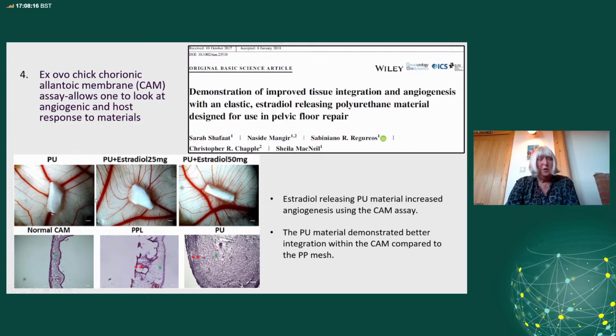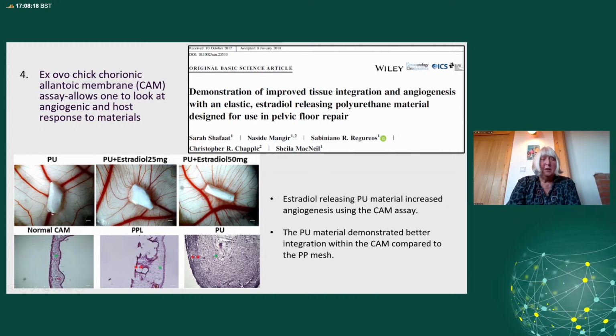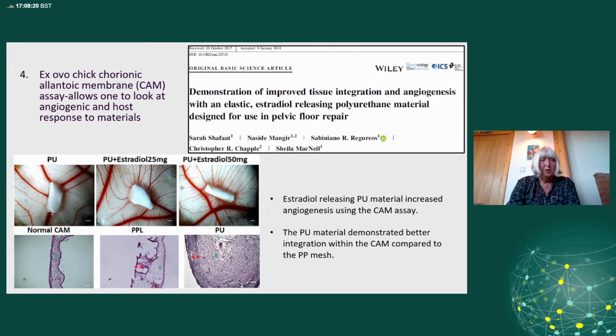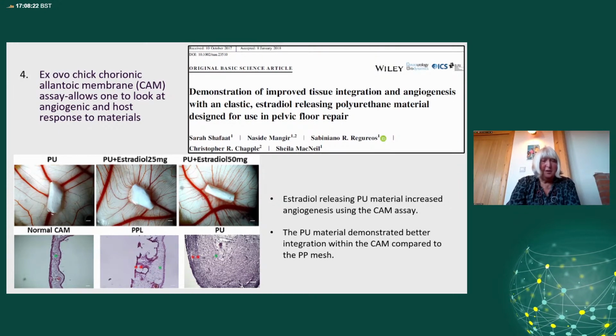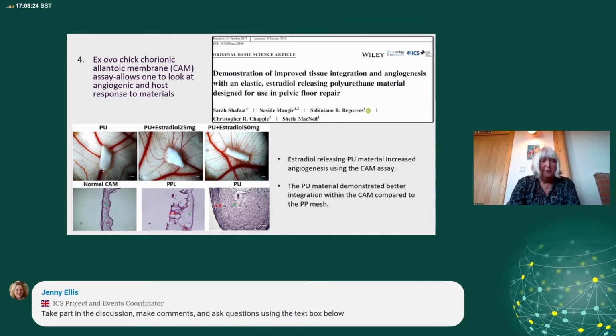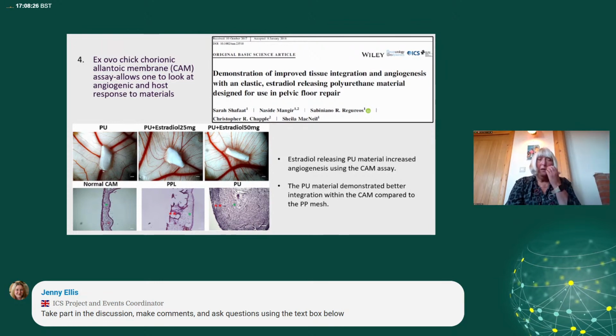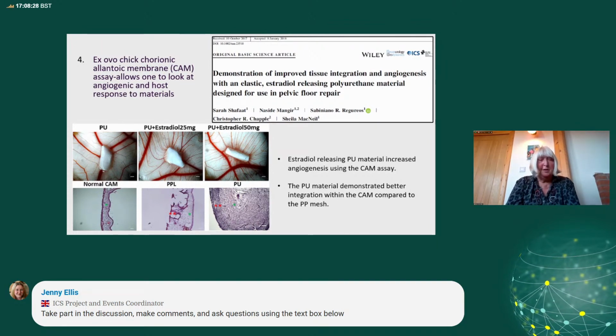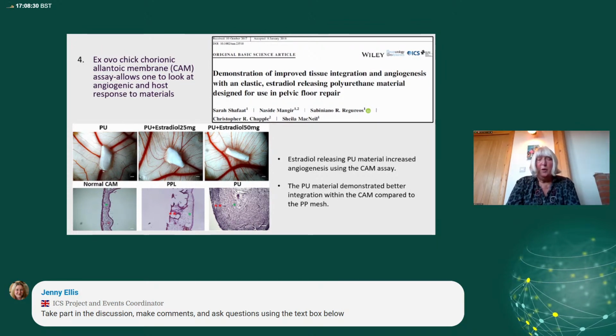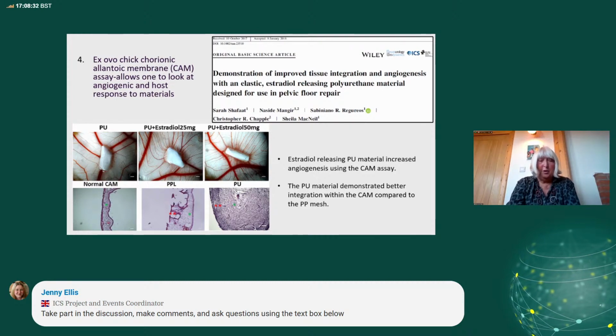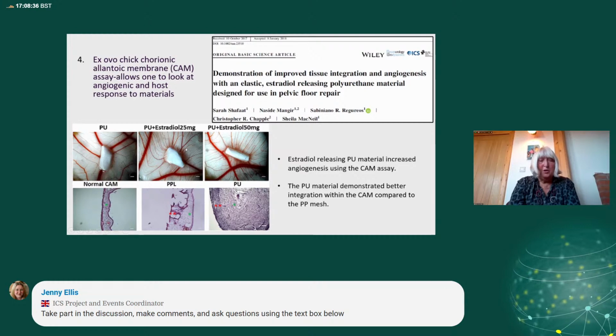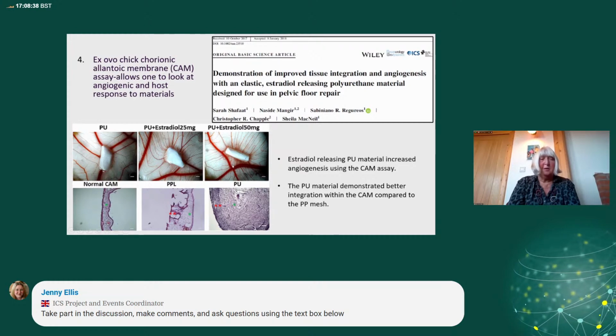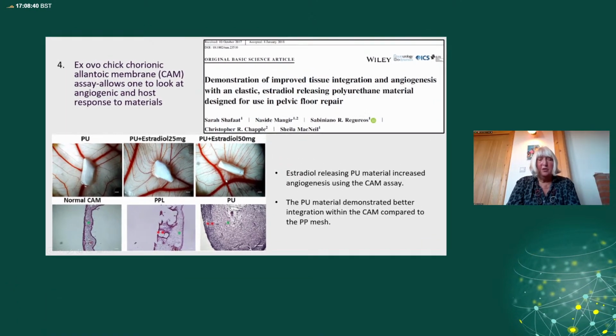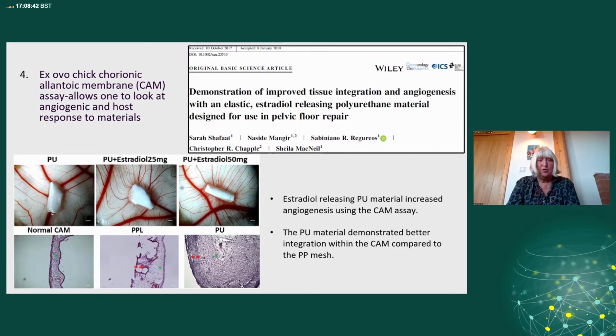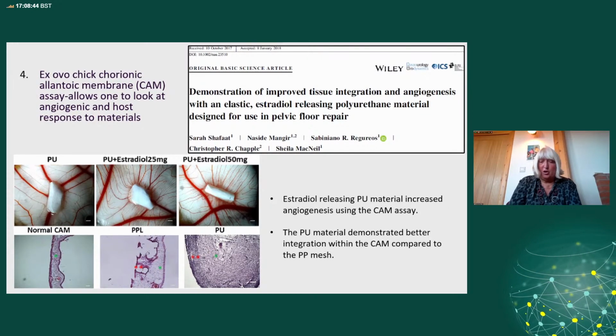Now, the real reason we use this model is we can look at angiogenesis. So you can put a piece of the material you're interested in, seen here in the top left, and this is polyurethane, and we see blood vessels moving towards it. If we introduce estradiol into the polyurethane, here seen as 25 and 50 milligram, what you see is a lot more small blood vessels. And the results of estradiol on angiogenesis are striking. So this is a direction for the future.